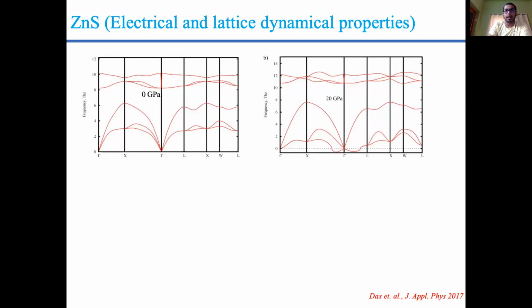At the ambient condition, we found stable acoustic modes. But when we go to higher pressure with the same crystal structure, we found negative acoustic modes. The physical significance of this negative acoustic mode is that the structure is unstable. We cannot find this structure at this pressure. As we already know from the phase transition curves, after 17 GPa the B3 phase transforms into B1. So this result supports our calculation.